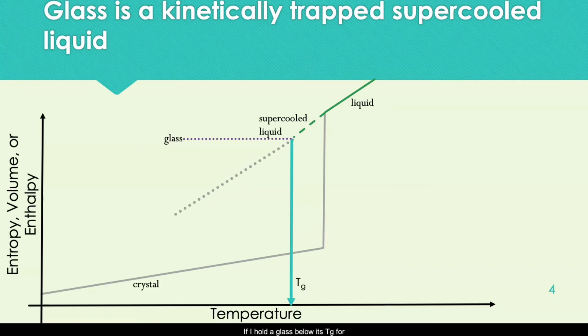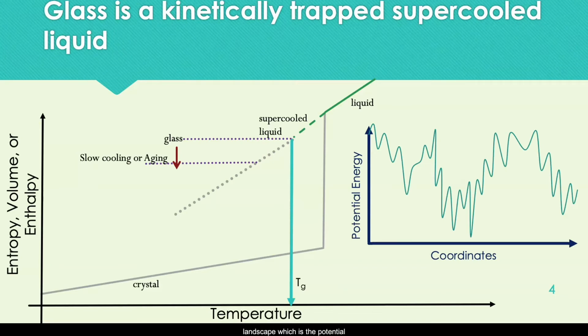If I hold a glass below its TG for some amount of time, because it's an out of equilibrium system, it'll move closer to equilibrium and farther down the supercooled liquid line in a process known as physical aging. So this is another way to achieve a glass farther down the supercooled liquid line. We can think of it by looking at a potential energy landscape, which is the potential energy as a function of all the coordinates of all the molecules in the system. So if I take a glass and I age it, it's going to very slowly move farther down the potential energy landscape into a deeper, lower energy state.